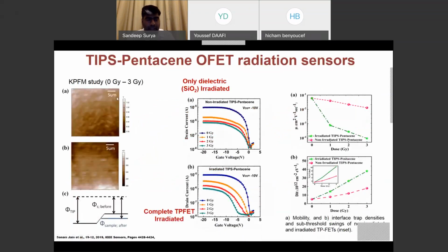As you can see from the KPFM images over here, the Kelvin probe force microscopy of the TIPS-Pentacene material without any exposure shows approximately 1 volt of surface potential. Whereas when it gets exposed to a minimal dose of 3 Gray, it comes down to 250 millivolts, which is around 1/4 of its initial value. This is the surface probing through scanning probe microscopy. The study has been done.